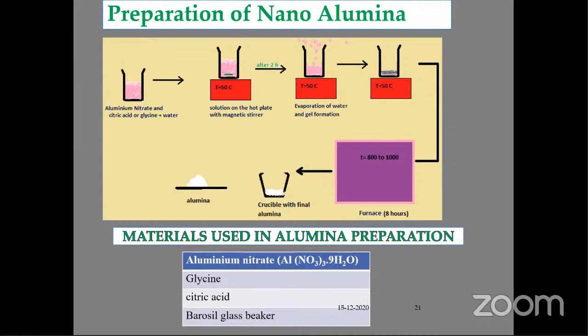So, some results straight away. When you use aluminum nitrate and citric acid as a combination with a 1 mole fraction of both, you will get the smallest nano size, almost 70 nanometers. But this is a bottom-up approach, because we are developing from the low level, converting the solid state into liquid state and then building it up. The maximum amount of particles formed will be in the range of 70 to 100. The formation will be within that range only.